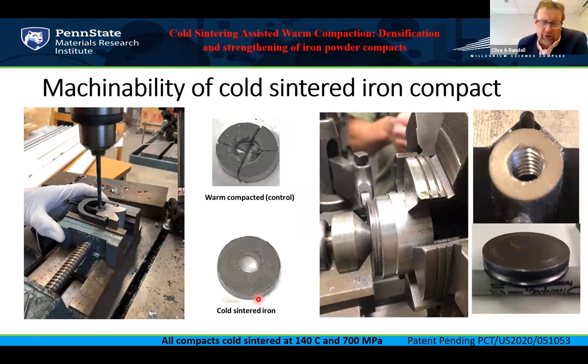There's a video here, which I'm not going to go into, but the technician doing this was cheering because he was able to thread and cut on a lathe a part that never saw a temperature above 140 degrees. It's quite fascinating because, particularly for hard materials, you could change the sequence of how you mill and shape and then control the firing for the tolerances that you need. And it also gives you an opportunity to mix hard and soft materials in the powder stage to make unique microstructures for strength.